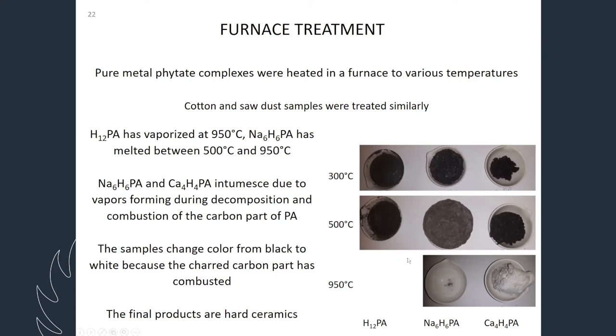The pure phytic acid start disappearing almost, and the calcium one still remain black. At 950, you can see the calcium one still has some black, but the sodium, it forms a crystalline phase, and that really becomes stuck at the bottom of the heating vessel. The Na6H6PA and Ca4H4PA, they actually swell up because the vapor that forms during the decomposition.